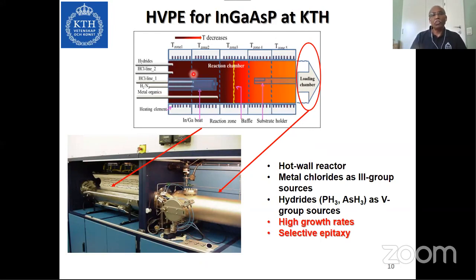And what you are doing here is actually generating metal chlorides as group 3 sources. So for example, gallium chloride and indium chloride. You pass HCl through gallium and indium, and you generate them in situ. And you have hydrides like arsine and phosphine as group 5 sources. And then they all come and react on the substrate, and you can grow indium gallium arsenide phosphide, for example.